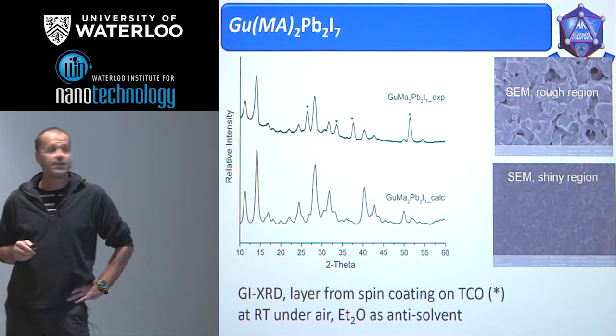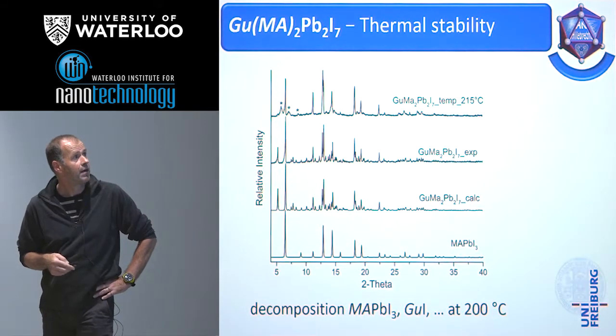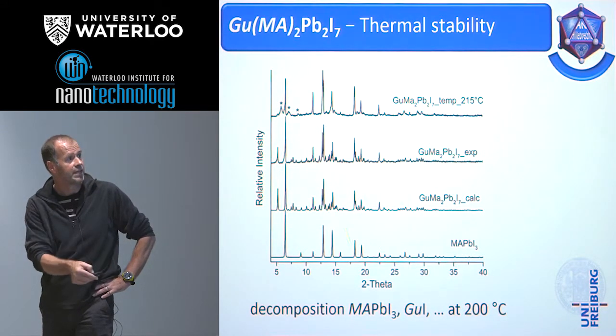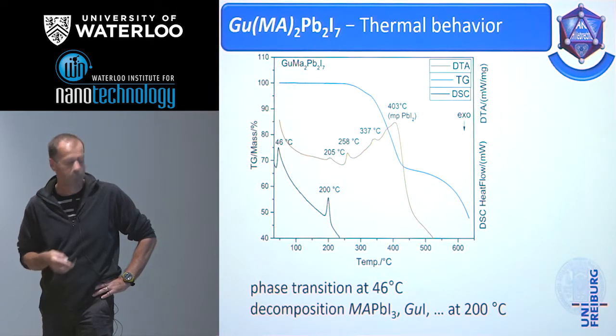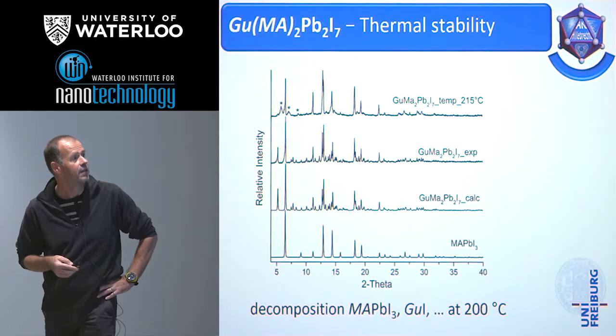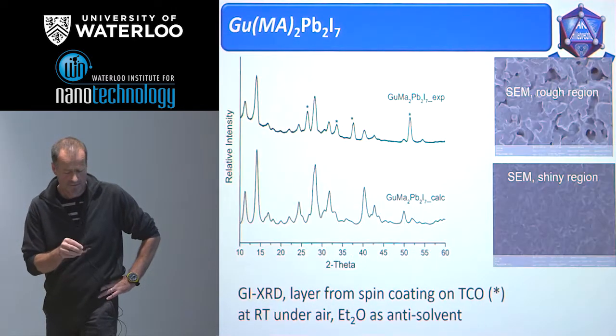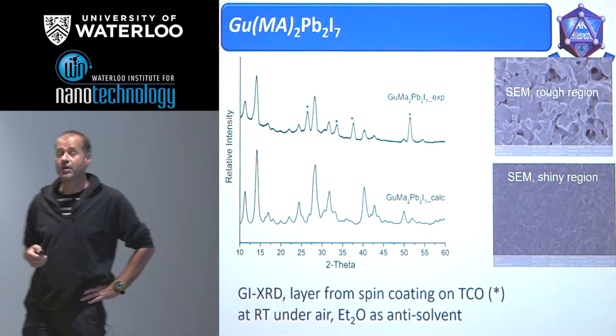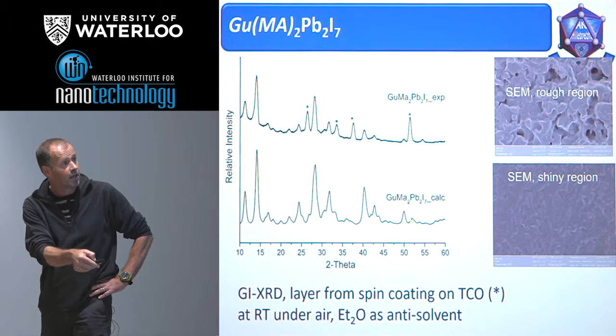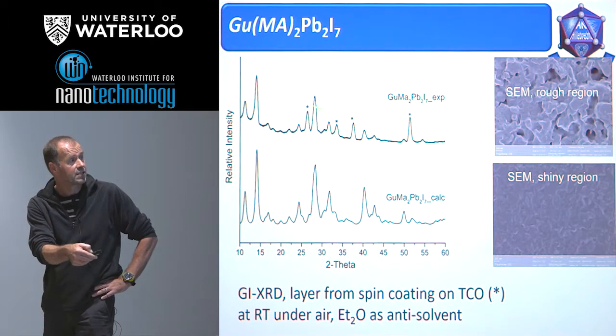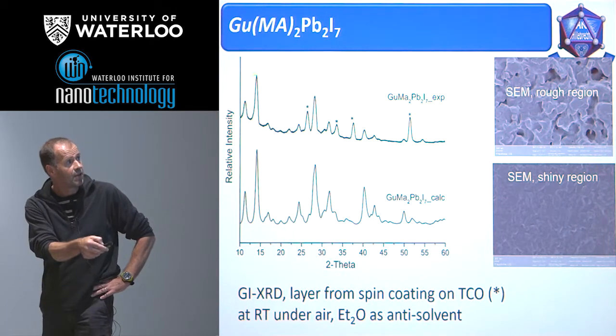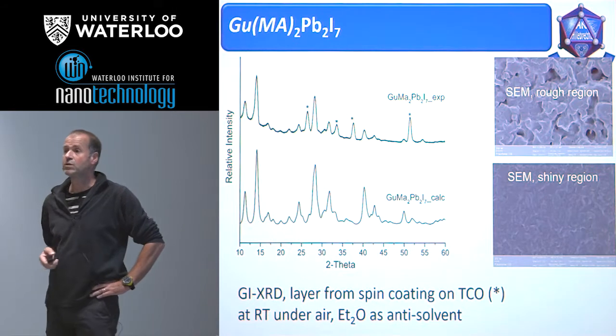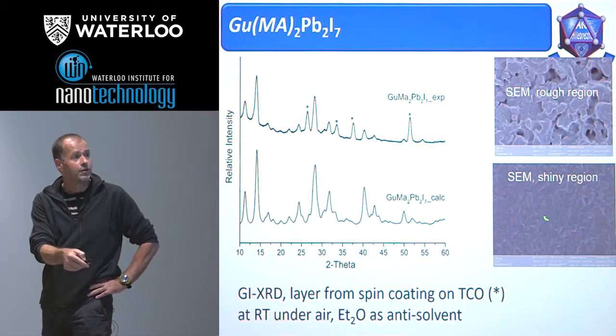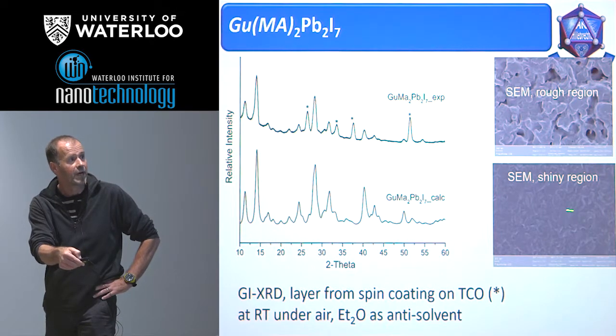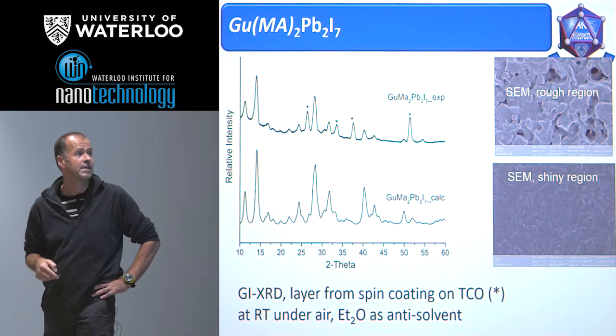Well, we could show that the active layer, the thermal stability, was checked by the X-ray investigations. It's quite clear. Now it works again. Yes, we investigated the layer and could show, according to the calculated and the measured X-ray pattern, that we have indeed as active layer our 2D perovskite. We could show that the microstructure depends a little bit on the optical impression. There are rough regions and shiny regions, but they all have the same composition.